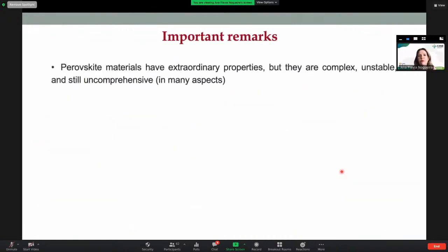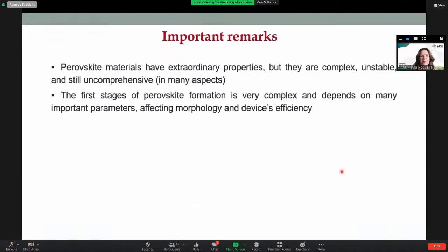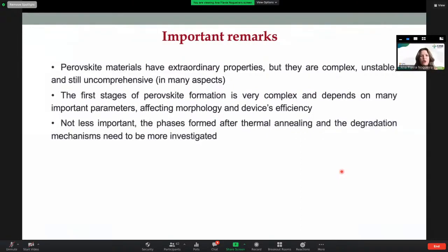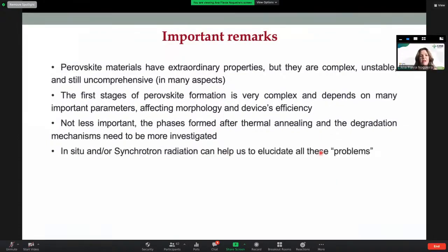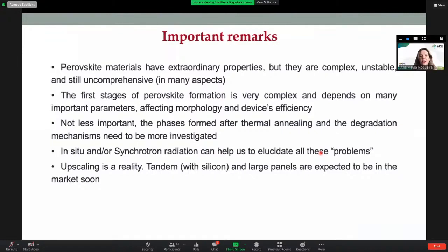So I've come to the end of my talk. I hope that I have convinced you about this fantastic material, the perovskites. I just want to show here that the formation is very complex, as I showed before, and not only the formation, but the degradation mechanism also needs to be more investigated in order to have more stable perovskites. In situ, with or without synchrotron radiation, is very interesting to elucidate some of these problems in the perovskites. And upscaling is really a reality. We're expecting to have these perovskite panels very soon in the market. Yes, there are a lot of things to be done.